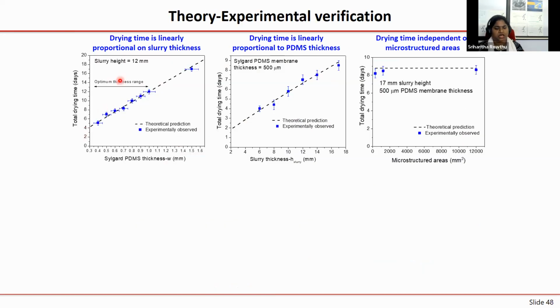So using these three conclusions from the theoretical model, now we needed to test experimentally. The theory is saying, let us focus on the first graph here, which plots my total drying time as a function of PDMS thickness W. The black curve is the theoretical one, and these blue points are the experimental points, which fit the theoretical observation very nicely. Then the second plot is drying time as a function of slurry height. Again, experiments and theory match nicely. Then the third point is that it is independent of the cross-sectional base area, right? I have done it here for 3 points, and you see that it again fits the theory.